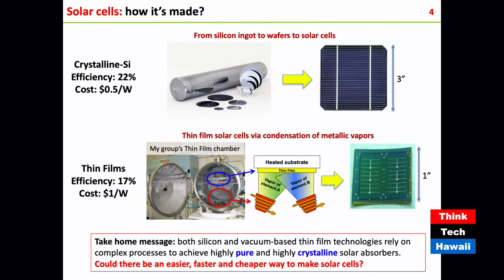Exactly. So once you get that ingot, you can slice the ingot into wafers. I've got one here, which was part of that ingot and was cut with a special saw, and then it's polished to the atomic level. So there is not a single atom that pokes through that layer. Oh, no, you're kidding. Atomically flat? Yeah. And then you cut that wafer further into squares because you want to be able to pack as many solar cells as you can, so a circular shape is not ideal. And then you build a couple more layers on top and you get your crystalline silicon cell.